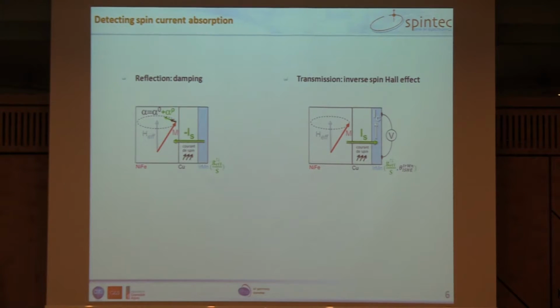To do that, we can do it in 2 different ways. Say in reflection, where we directly have a look at the nickel iron damping, or the nickel iron resonance, and in transmission, where we directly have a look at the spin to charge conversion in the antiferromagnet. So I will show some results in these 2 conditions, and I will start with this reflection.